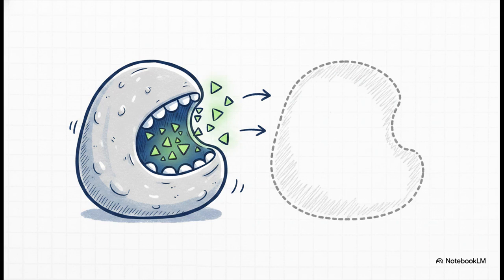But wait, what actually happened to the S2 mix, the one with just 2% lime? Crucially, that middle mix lost strength compared to the baseline. Why? Well, it's because of a chemical phenomenon called lime fixation. The clay in the soil actually has a natural appetite for lime, and it absorbed that entire 2% immediately. It just ate it all up, leaving absolutely no free lime left over to trigger those incredible long-term strength-building reactions we saw in the S3 mix. It's a textbook example of why getting the exact ratio is so critical.